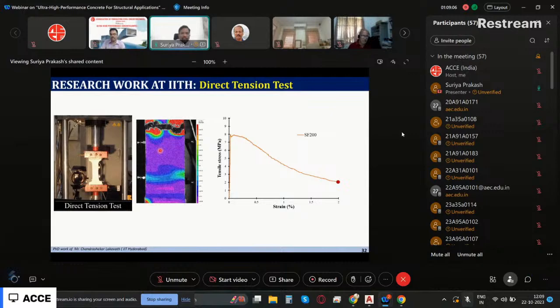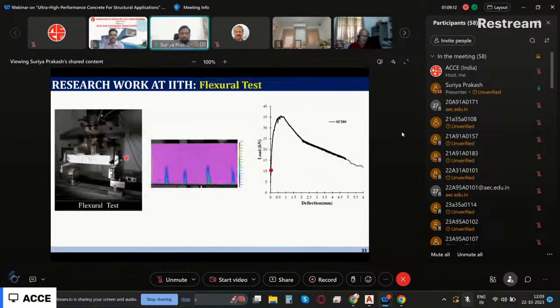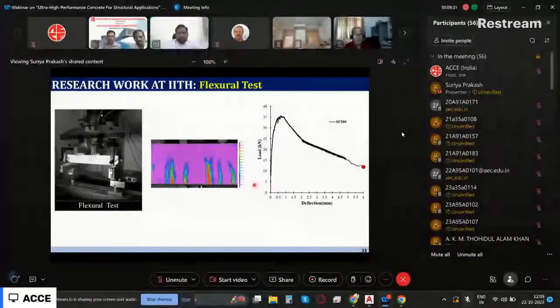And that is the reason we are very confident that this particular technology will work really well. And this is the flexural test I told. At about even, you can see multiple cracks are formed. Not just one crack, you now have multiple cracks that are formed. Whenever your system is able to generate a large number of small cracks, that means the performance is good.